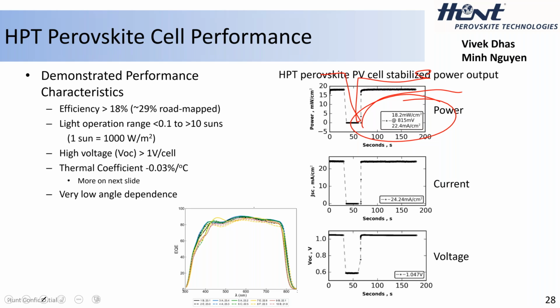Further, this cell also has a very small thermal coefficient. We measure around negative 0.03 to negative 0.05, typically somewhere in that range. And we'll show you how we do that here on this next slide.